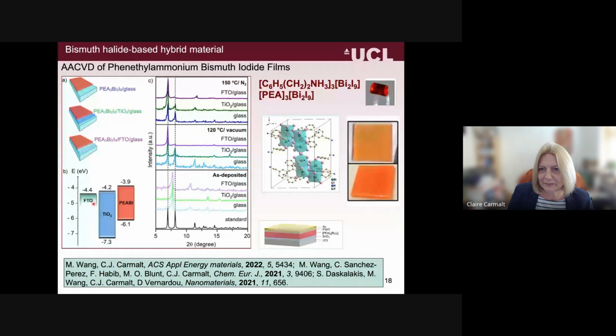We looked at the band alignment and decided this is our bismuth iodide, and we decided to deposit it on plain glass, also on TiO2, which had been deposited on glass, and on fluorine doped tin oxide. Now, as deposited, you still see peaks due to the solvent. We have to use DMF as the solvent, and so you have to anneal it to get rid of the DMF. So you either can heat that up in vacuum at 120 or under nitrogen at 150, and then you get a good match to the standard pattern.